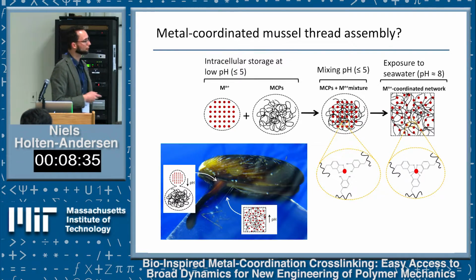Part of the trick that we realize the mussel is probably using is that when these ingredients initially get mixed, it takes place at a low pH, and that has now been documented to be true as well. The initial secretion of the metal ions and the polymers, when mixed together, occurs at a low pH. This matters for the crosslink chemistry because at low pH, the organic ligands that bind the metal ions interact only weakly with the metal ion—not strong enough to make a solid crosslink, but enough that they can still move around, self-assemble, and sit in the material hierarchy where they need to be.